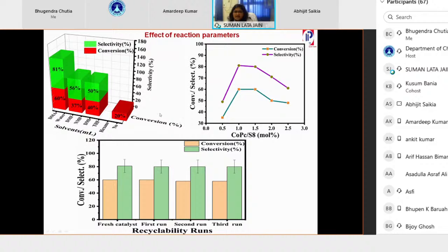These are the effects of reaction parameters. We screened a number of solvents. Among all these, DMA, dimethylacetamide, is found to be the optimum one because it has a binding tendency with carbon dioxide, so it is called a CO2-philic solvent. So it increases the concentration of carbon dioxide in the reaction medium, and that is one of the main reasons for its higher reactivity. Similarly, we optimized the catalyst dose.